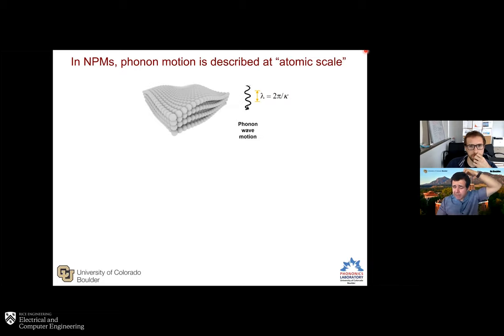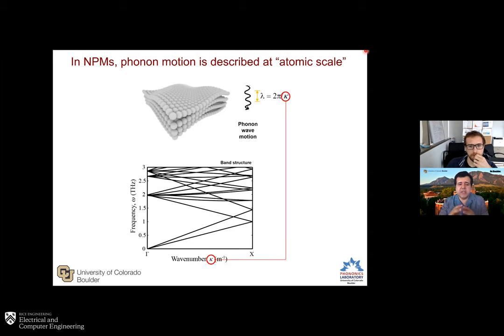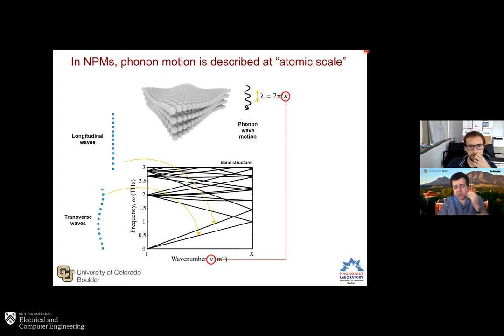So I'm going to go ahead now and run by you a few slides that describe, in a very, very simplistic way, how we've built our models. So again, this is the strip that we have, and it's admitting phonons. Each phonon is described by a wave number, so we can construct a phonon band structure. In this case, the bands are all folded, because it's modeled as a supercell, and we can identify the various modes of propagation, transverse waves, longitudinal waves, and so on.